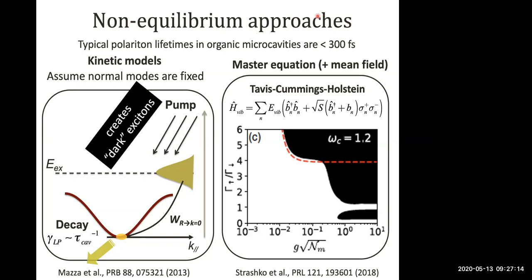Two approaches have been used to model organic polariton condensation. One is to use a simple rate equation, a kinetic model. In this case, we assume that the normal modes are fixed, and scattering rates between initial and final states are calculated using perturbation theory. This is what we did, for example, in modeling condensation in anthracene. In this sort of model, we have some pump term which populates initially our reservoir of dark excitonic states, and these then scatter to different states along the lower polariton branch, and you can also have interbranch scattering. Generally, the dominant contribution is the one coming from dark states directly to the bottom of the branch, and in this kind of model, the condensation threshold corresponds to the situation where the net scattering to k equals 0 is equal to the loss rate from k equals 0, which is just given by the polariton lifetime.